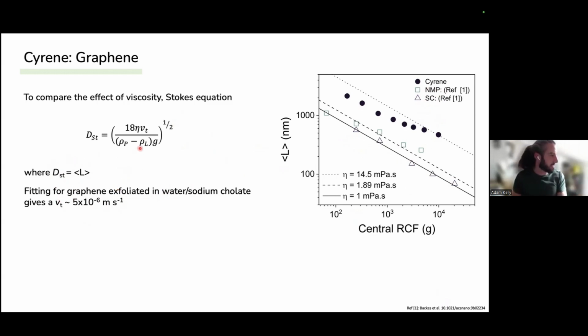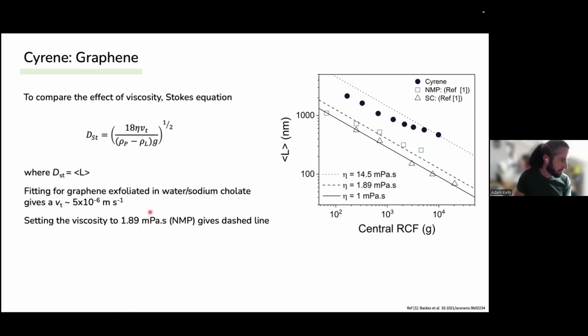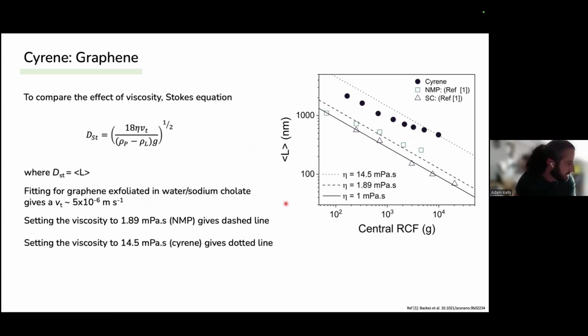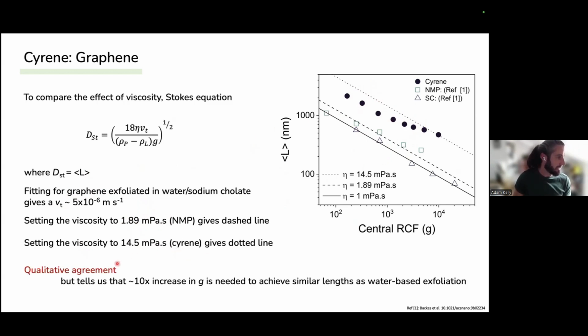So usually the problem with using this equation is that it's difficult to get a terminal velocity out. So if we want to assess the effects of viscosity, I'm going to hold this terminal velocity constant and then increment the viscosity up to that of NMP. And that gives us this dashed line here, which we find qualitatively agrees with the NMP data from reference 1. And then if I set the viscosity to that of cyrene, which is this dotted line, again, agreement's not great, but it is qualitatively similar. But what is good about this is that it tells us, because of the increased viscosity of the cyrene, we need a 10 times increase in the central RCF, in the g-force, to achieve similar lengths.